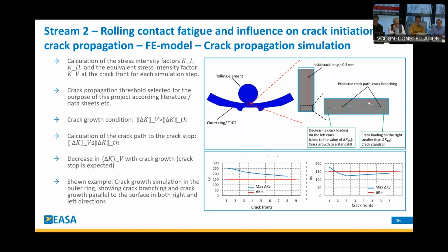Based on the pre-work of the FE model, and of course the setup of the calculation, the crack propagation simulation analysis has been done. I would like to start with the analytical description on the left side. The calculation of the stress intensity factors K1 and K2 and the equivalent stress intensity factor KV was done on the crack front for each simulation. Now let's look at the picture here. We have the rolling element and the outer ring. We have the initial crack length, and then you will see different colors. Each color is representing one simulation step, one increment. So this means it's one calculation, then the next calculation, the next calculation. This has been done for each of these crack fronts.